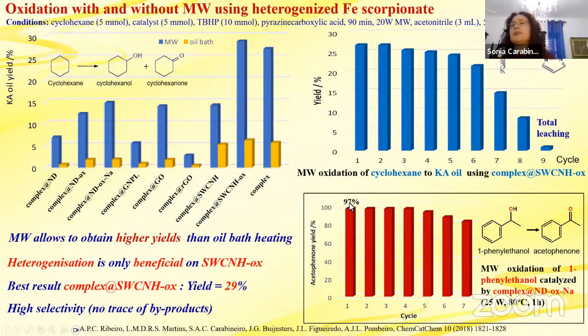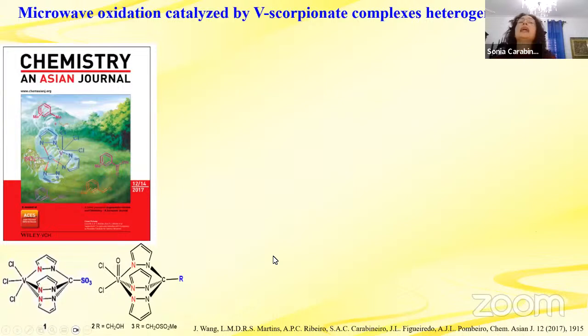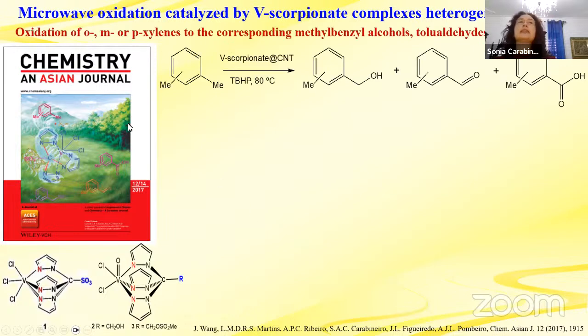could obtain 97% yield and a very good recycling, a little bit of activity loss, and just 1 hour for the alcohol oxidation. We also tested the microwave oxidation catalyzed by vanadium scorpionate complexes on carbon nanotubes. This was also a cover of this journal, Chemistry: An Asian Journal.